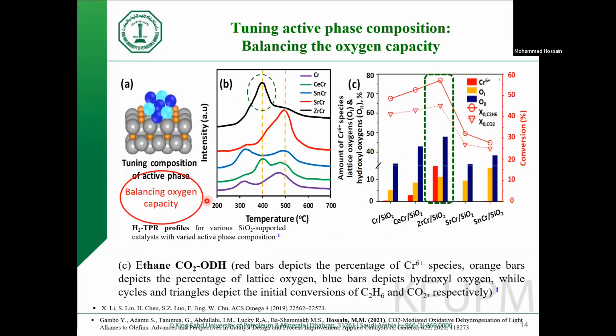Another approach is balancing the oxygen carrying capacity, and this again goes back to the reducibility of the catalyst that can be achieved by using a second metal. So in this case, chromium was promoted with different oxygen carriers or supports, in this case ceria, and then Sr, Sn, and zirconia, and so on. The black line, which I believe is zirconia, brings good reducibility of the catalyst, and that has been reflected here as a good conversion of, in this case, ethane and CO2.